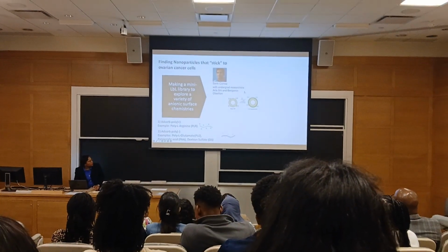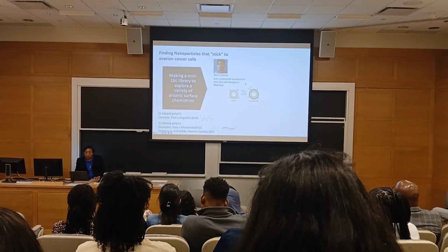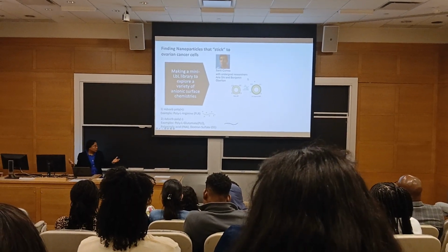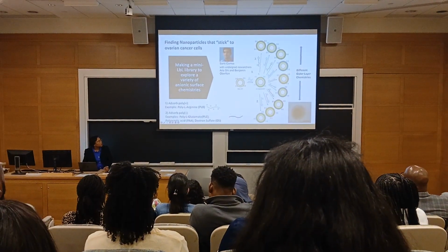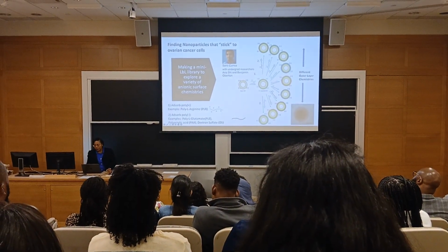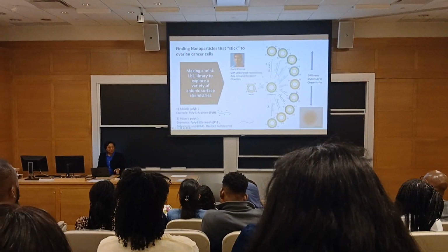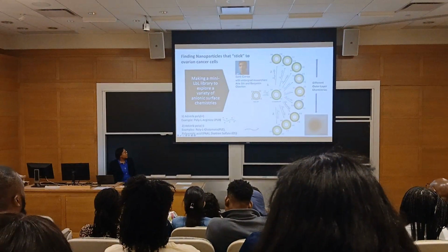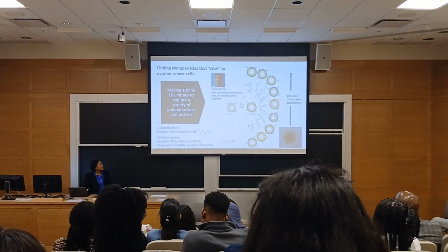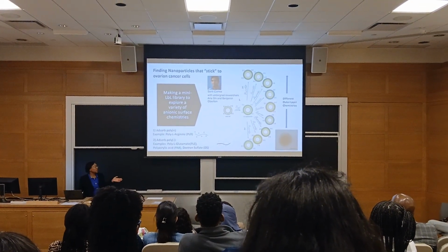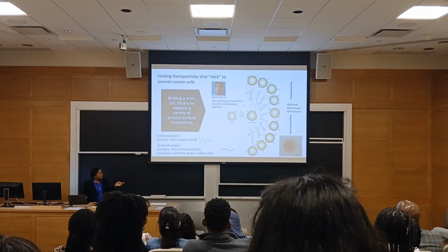We took a negatively charged liposome. We absorbed poly-L-arginine, which is a positively charged polypeptide. And then we absorbed a number of different negatively charged polypeptides. We went to Sigma, we ordered a bunch of known negatively charged polypeptides, and we just tried them. And out of that group, there were 3 of those polyelectrolytes that were particularly interesting, 2 that we've been working with a great deal to address ovarian cancer.